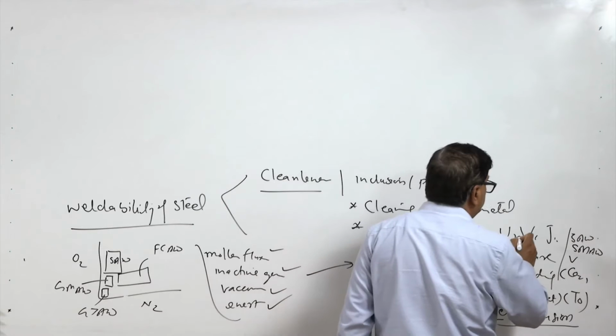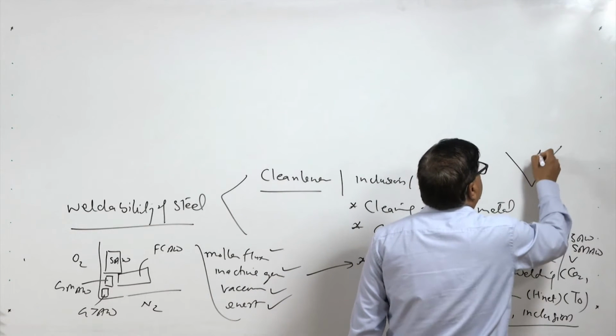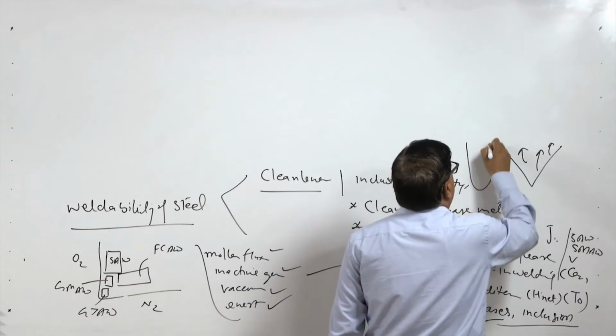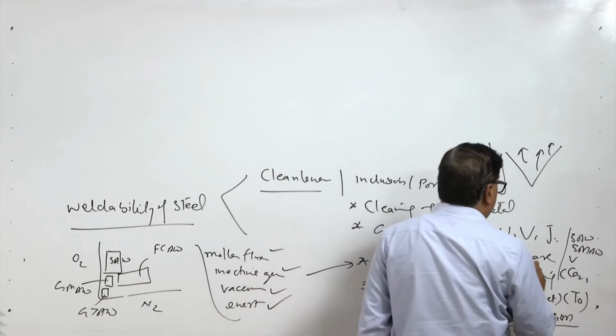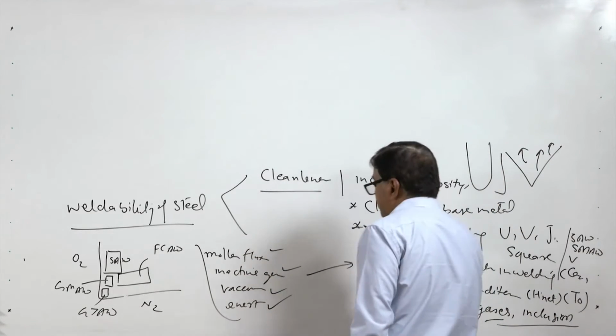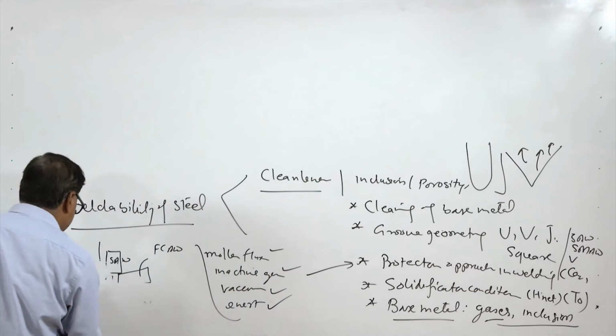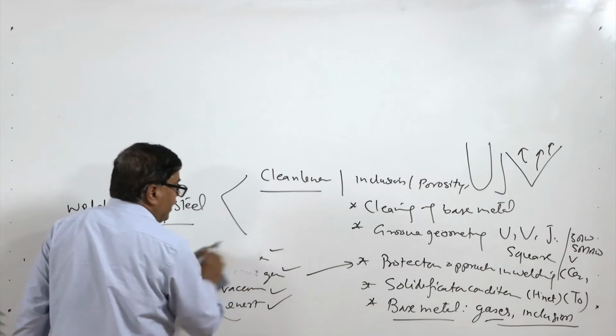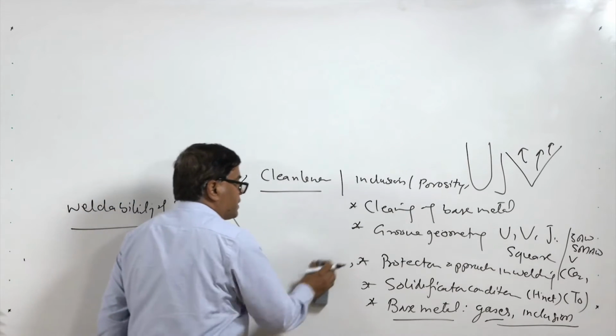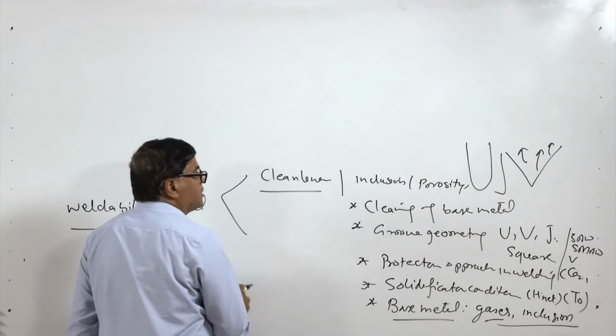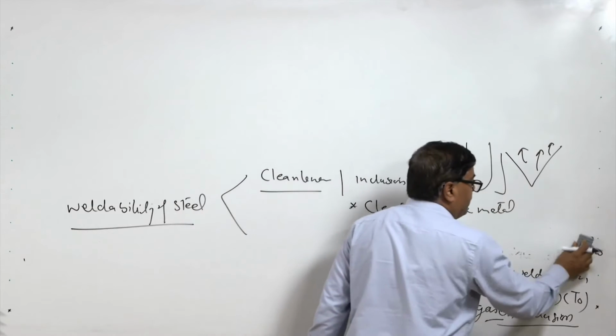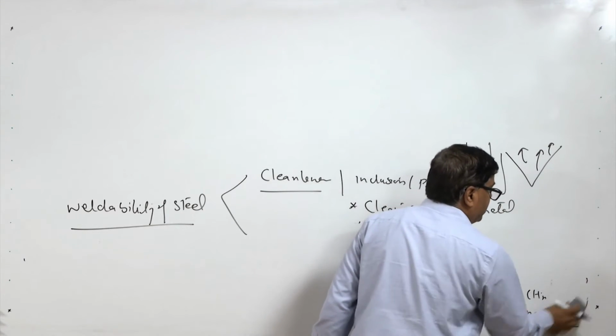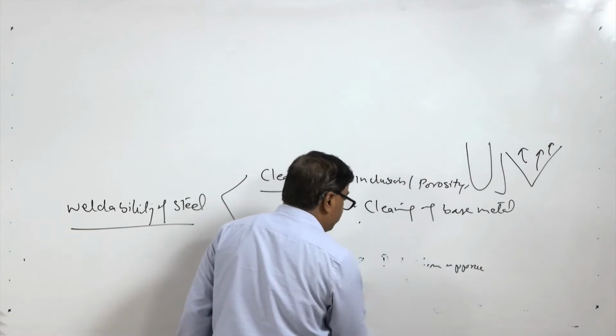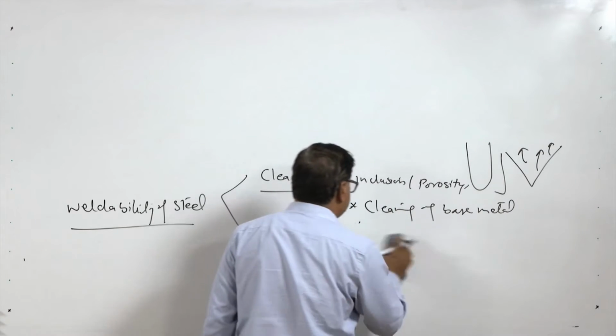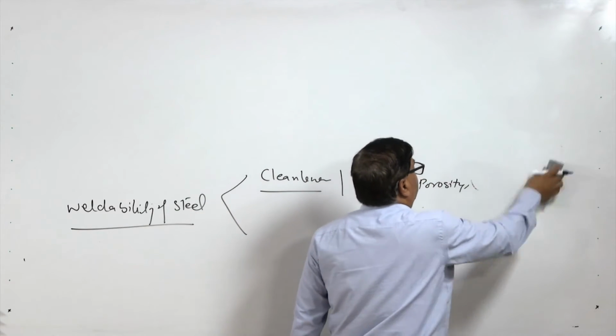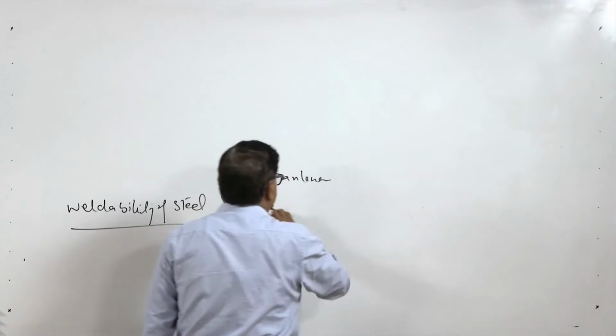The groove geometry, the U, V, J. The V groove geometry allows sufficient opening for the gases to come out as compared to the U and J kinds of geometries. Then we have the cleanliness of the base metal. If oil, grease, paint etc. is left on the base metal surface, under the influence of the heat these will evaporate and get mixed up with the weld metal, and produce inclusions and porosity in the weld metal. So, cleanliness of the weld metal is affected by a number of such factors related to the welding procedure, and these need to be taken care of.